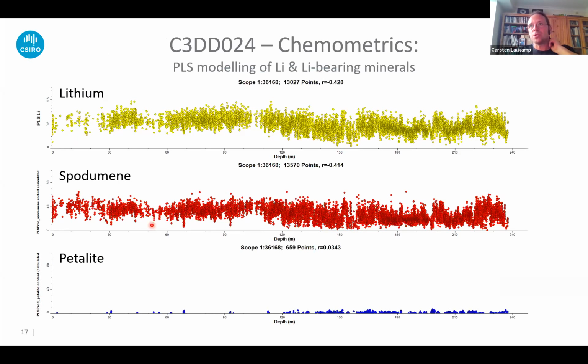If you have the geochemistry, I showed before the downhole plot of lithium content. This is now when we train the hyperspectral data with the lithium content, and this is the predicted lithium content down the drill core. At the top, we have a little bit more lithium than further down, and that correlates somewhat with spodumene content. We've got maybe some petalite also, another lithium-bearing mineral, further down in the drill core.